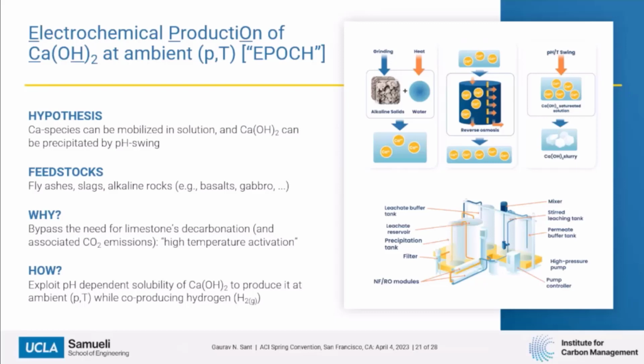So it's something that we've worked on for about a decade now. This work has been funded by the Department of Energy. And really what we were interested in was taking feedstocks that are alkaline. Take fly ashes, take slags, take alkaline rocks like basalts and gabbros, and put them in a solution. Once you put them in a solution, you can essentially start to selectively take out all of the calcium to produce calcium hydroxide.